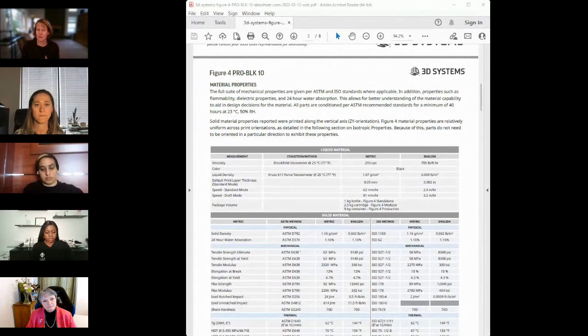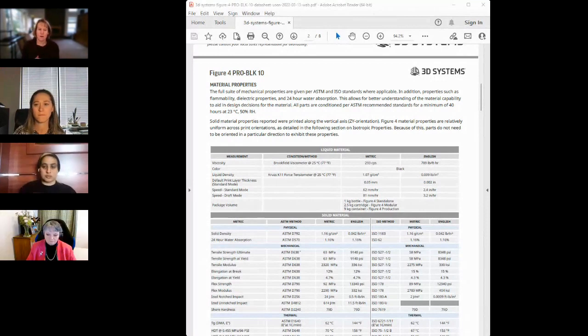For example, our lab is climate controlled, so we maintain a 22 degrees C and 50% humidity environment. We also make sure that the specimens meet the ASTM standards regarding their geometry and surface finish. And sometimes that does require some additional finishing in order to meet those standards. Fortunately, with the photopolymer technologies, it's relatively easy to meet the requirements, but you can imagine it can be much harder with the lower resolution technologies to meet those standards. And we are well aware that the standards were not written for AM materials, so my team is also very involved in ASTM and on some of the committees working to make those standards more inclusive of AM materials.